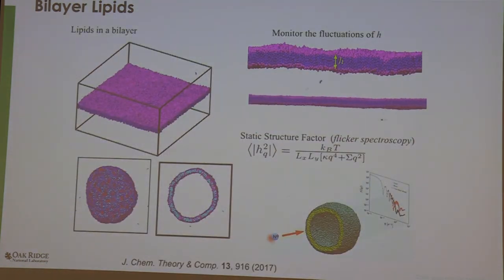Another example is looking at bilipid layer dynamics in vesicles. I already showed you the cell membrane, so this is just another example of that. Here we're, again, looking at phase separation. Instead of forming pores, we're looking at just segregation of lipids in a lipid bilayer or a vesicle. A lot of people believe they do form these little domains. These domains are tiny, and the time scale that they form on is short, so it's hard to experimentally observe.